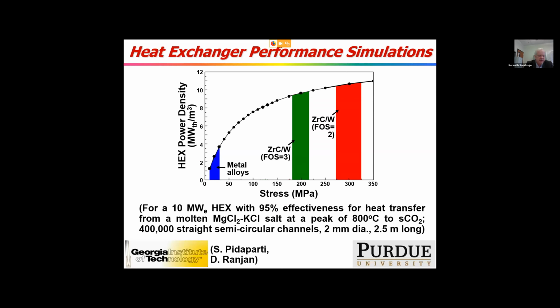Well, because the ZrC-tungsten does have a much higher failure strength, what that allows you to do is to make the plates much thinner for the stresses that are applied, say, with high-pressure supercritical CO2 in a heat exchanger. This is an initial calculation done for us by Sandeep Pitapparti and Devesh Ranjan, Professor Ranjan at Georgia Tech. Ashay's group has been continuing to do some of these types of calculations for us with modified geometries. Because the metal alloys do not have as high a failure strength, the plates need to be made thicker, which then means that the power density, the megawatts of heat per cubic meter, is much lower.